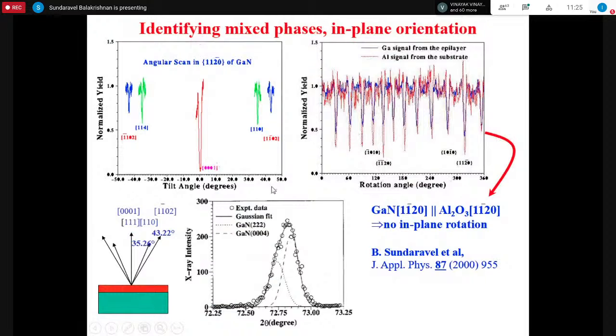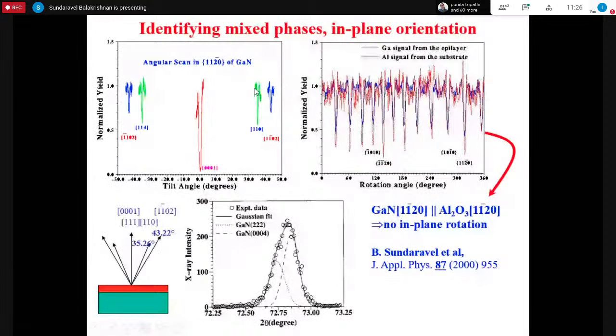And then in the case of gallium nitride, I told that we can find mixed phases with channeling. So about this normal axis, if you tilt by 35.26 degrees, then one can see a 110 orientation on one side and 114 on another side. And this sample shows that there is this cubic phase. The green color shows this cubic phase content, and this blue color tells about your hexagonal content. It can also be seen with XRD. So different peaks correspond to different components, different phases, and one can tell about it.